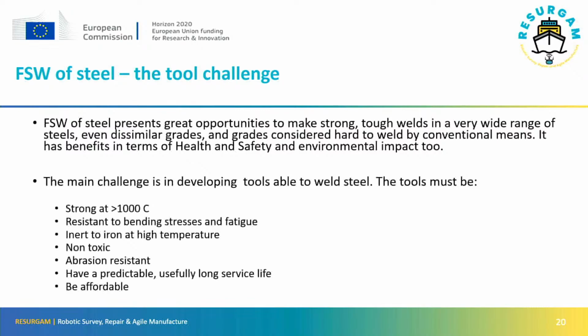One of the big problems we've faced with transferring the technology of friction stir welding from aluminium, magnesium, copper and titanium to steel is actually developing the tool to do it. Because what we're actually looking for is a tool that can stir steel. And that steel is at about 1,000 degrees centigrade. And if you think about it, there aren't many materials which are stronger and stiffer than steel at that temperature. Because the tool's rotating and being pushed through the metal, it sees quite high bending stresses and fatigue loads. And again, a lot of materials can't tolerate that.